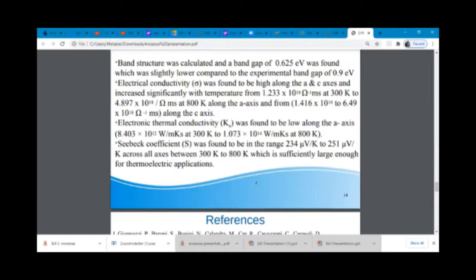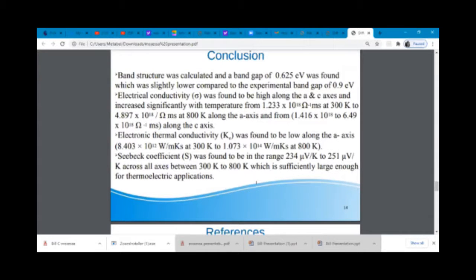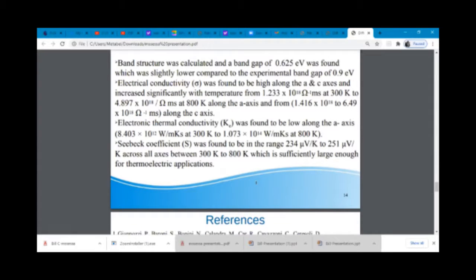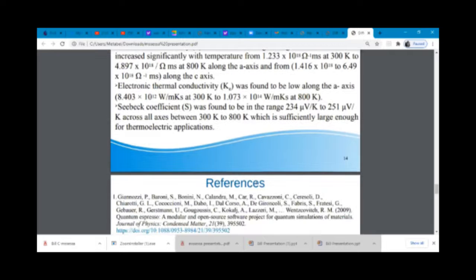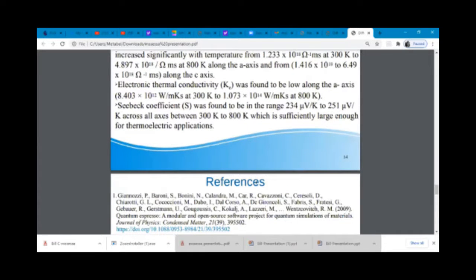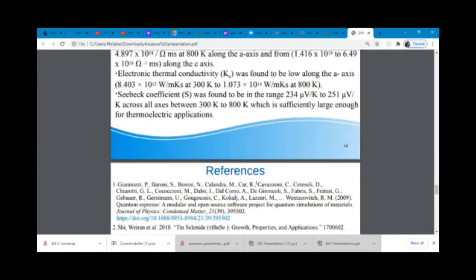On the other hand, the electron thermal conductivity was also found to increase with the temperature, but was low on the A-axis. The Seebeck coefficient was found to be in the range of 234 microvolts to 251. It is also a very good value. It is sufficiently high enough, if not excellent, and is enough for thermoelectric applications. So here are the selected references that I've cited.